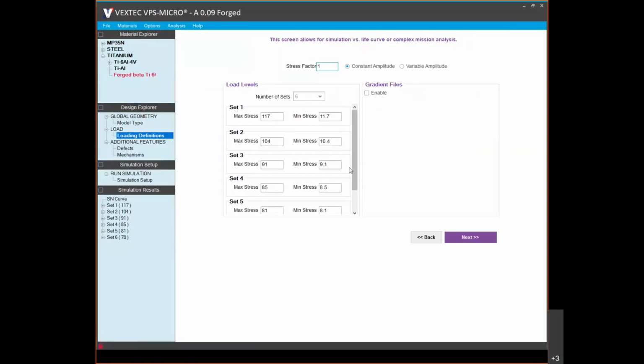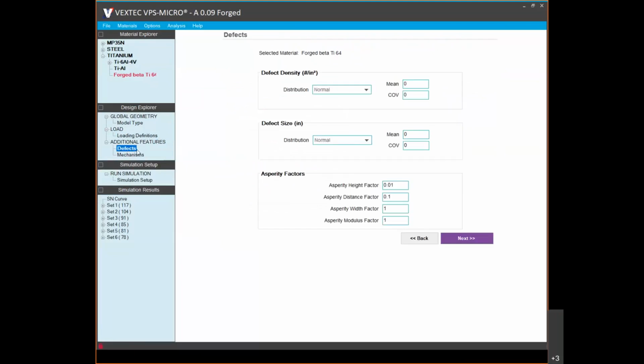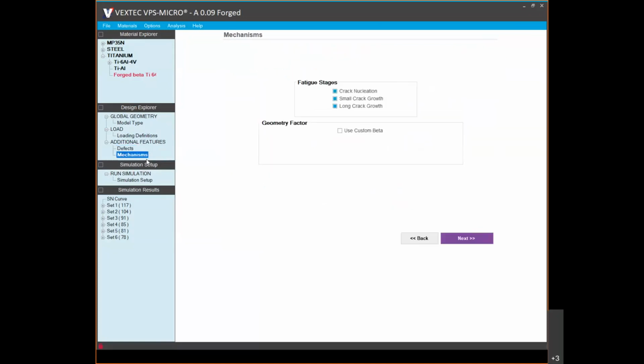And the final step of the Design Explorer is additional features like defects, the probabilistic population of these microstructural defects, the voids, the pores, inclusions, the non-melt areas, as Bob described. For our forged example, we have none of these. Also, there are asperity factors available, which model the tortuosity of the fatigue cracks as they propagate. Other features in the software include the options for computationally modeling the individual fatigue stages, the crack nucleation, small crack growth, and long crack growth, as well as custom geometry factors or beta factors in the fracture mechanics simulations that VPS-MICRO performs.